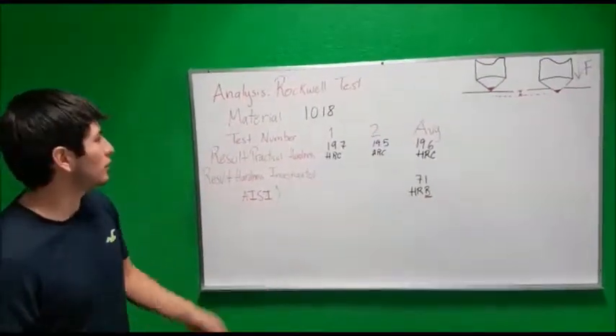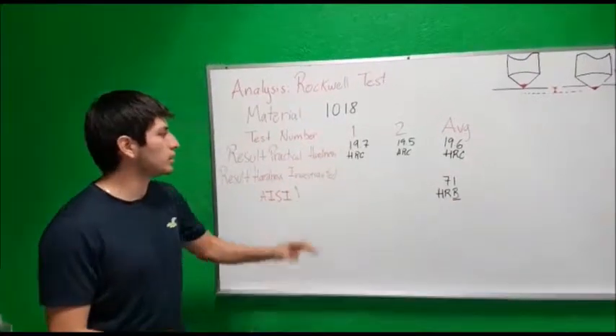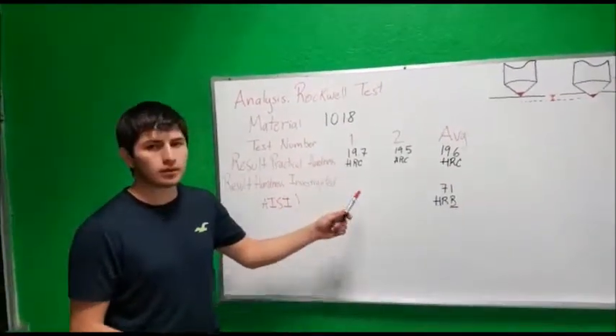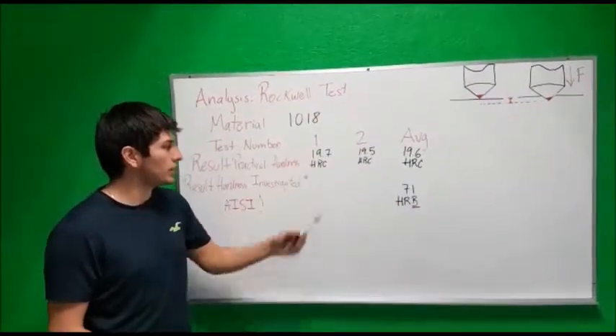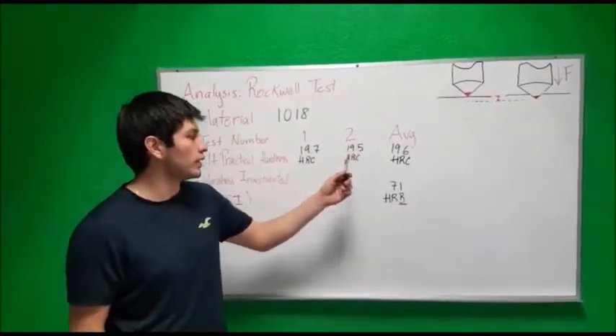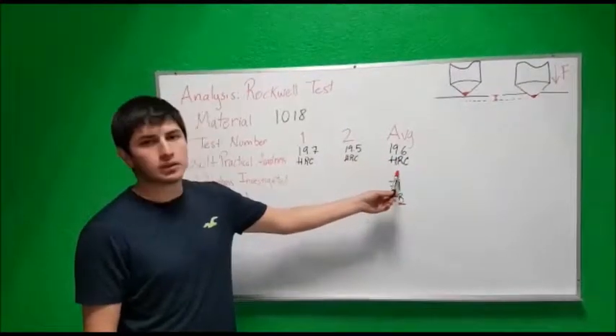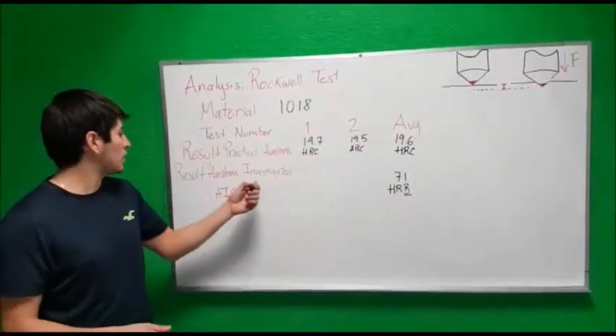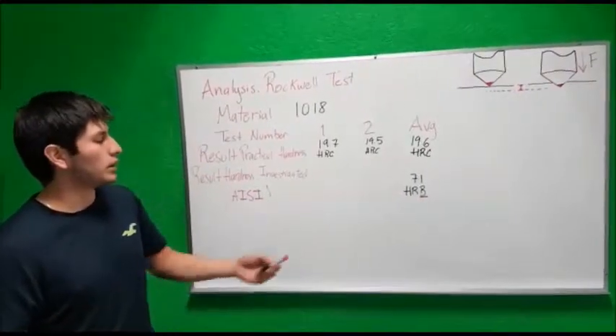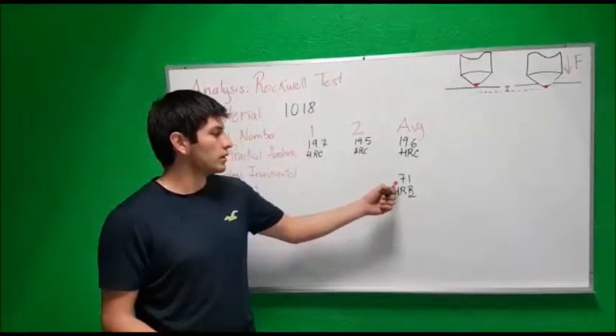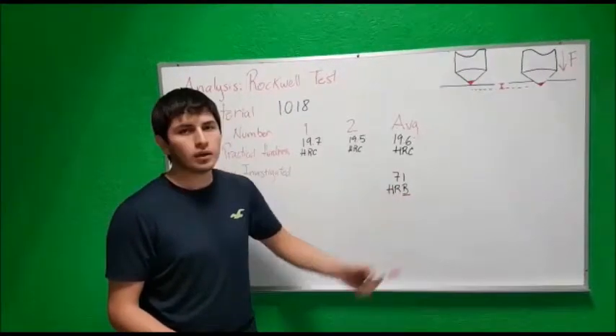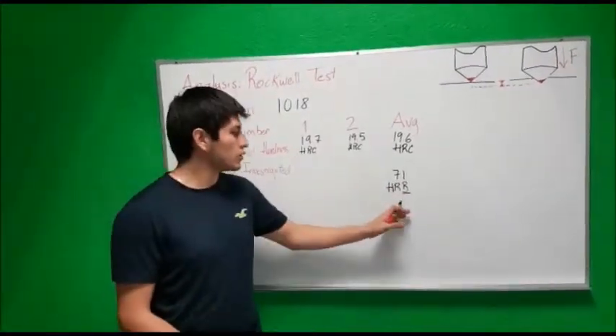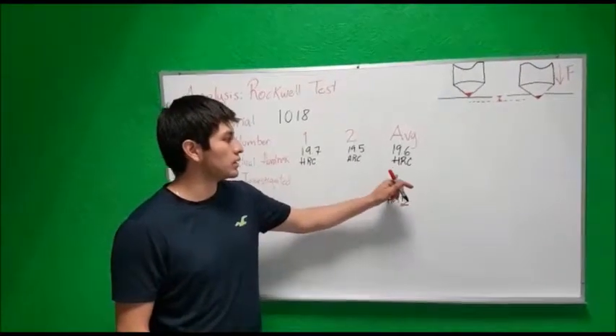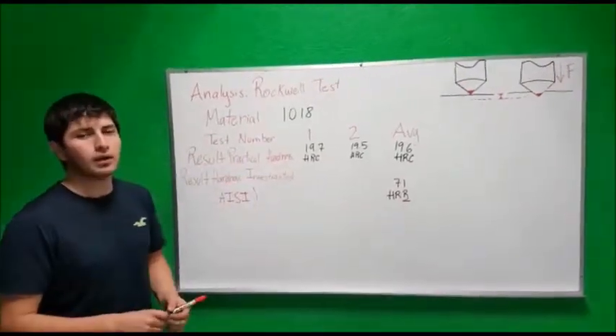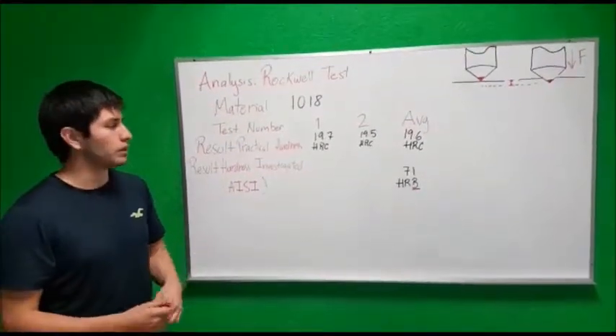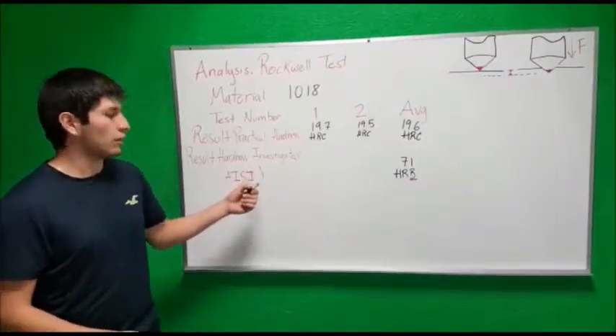In the Rockwell test for the steel 1018, we get these values. In the first measure, we obtained 19.7 HRC. In the second, 19.5 HRC, and the average is 19.6. When we investigated the hardness results, we only found 71 HRB, but we can't compare this one with this one because this is HRB and this is HRC. So we don't know how far we are from the official result.